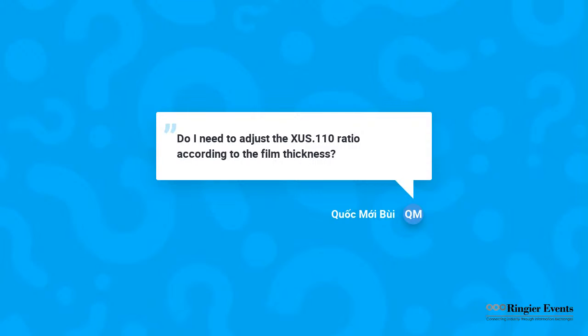The film structure and the film thickness will have an influence on the final COF of the film. So you have to consider your total thickness and also your layer ratio of the COEX PE film to adjust the ratio of the XUS 0.110 in the sealant layer. For example, if you have a film with 15 micron thickness and the layer ratio is about 3:3 layer ratio, for this kind of film you have to add 50% of XUS 0.110 into the sealant layer to ensure a stable and low COF.